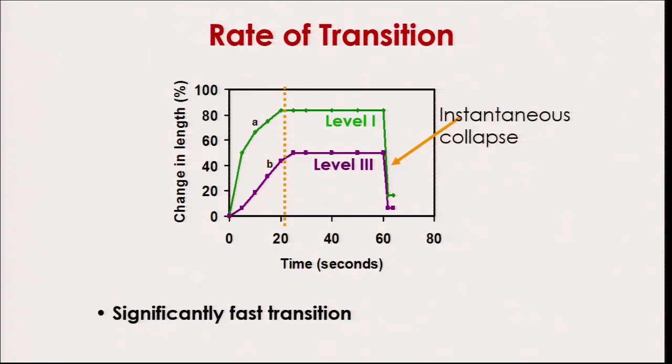Importantly, when you change it from high temperature to low temperature and back to high temperature, you do not observe any hysteresis. It follows the same path, which is very important for any application. Looking at how fast this transition occurs, if I have a fiber, the transition occurs in a time of less than 20 seconds.